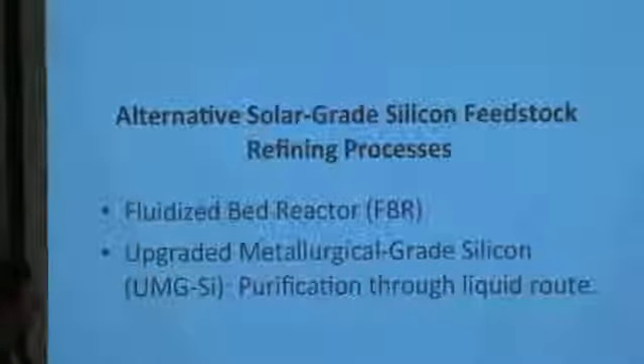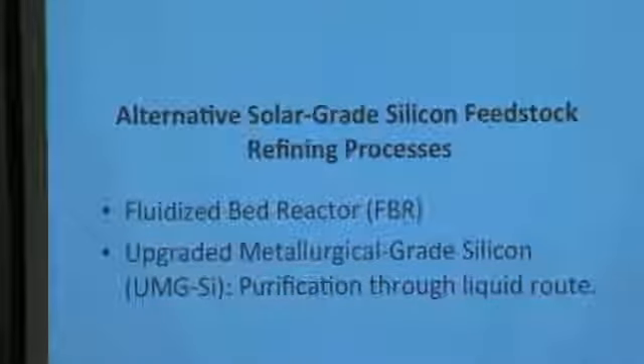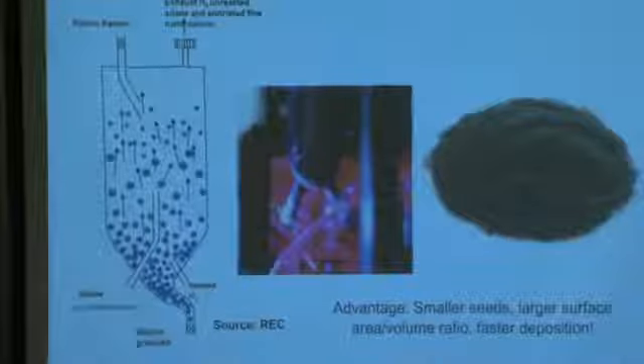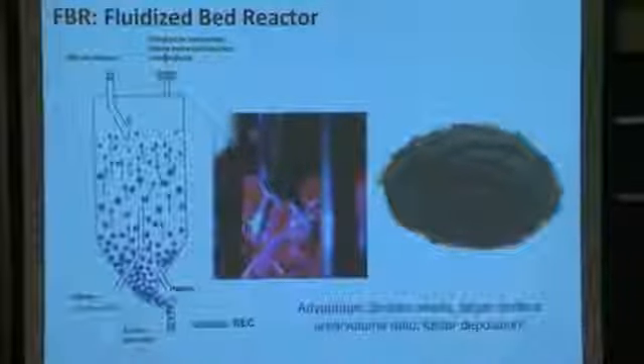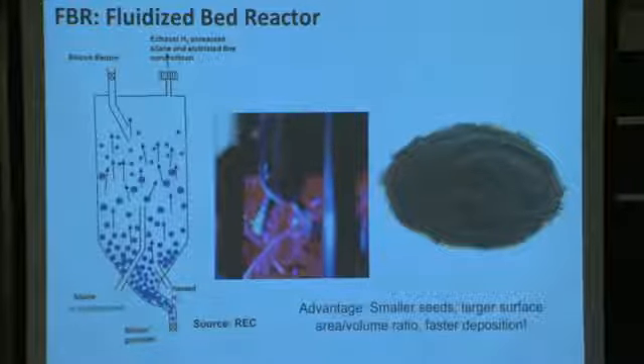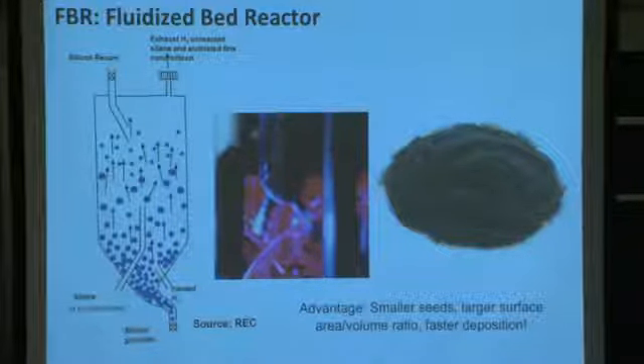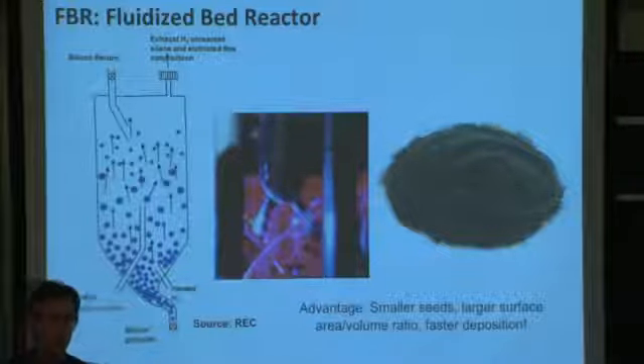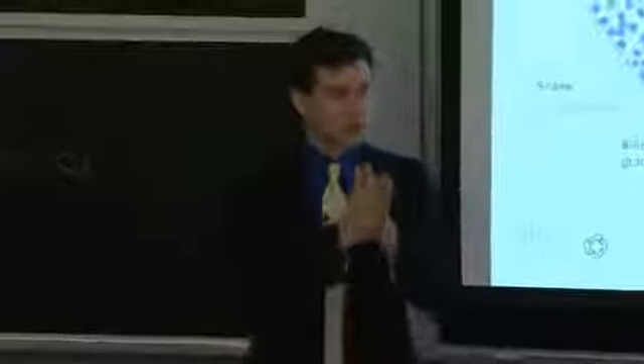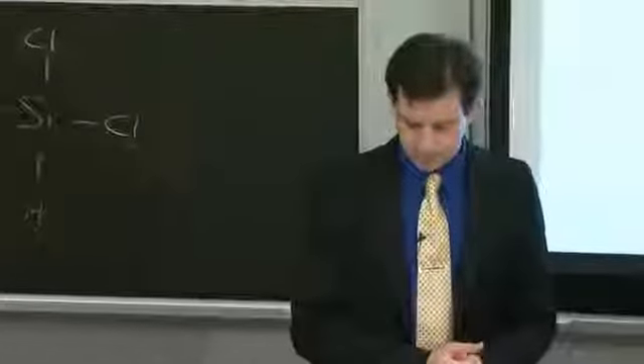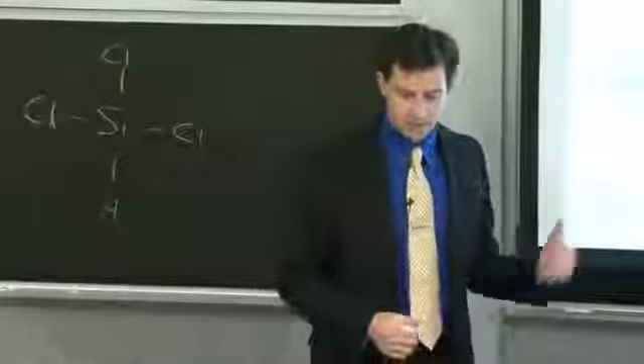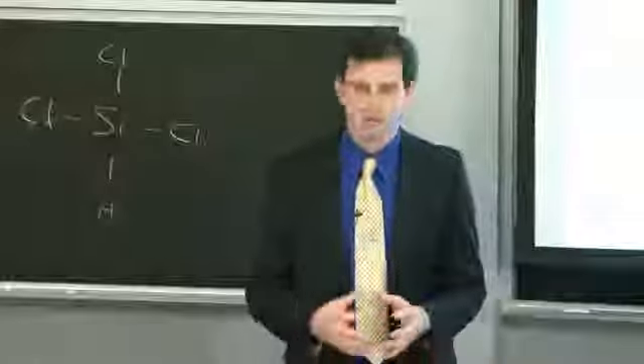So fluidized bed reactor and upgraded metallurgical grade silicon. Let's talk about each of those in turn. What the fluidized bed reactor folks realized was, gee, if we're depositing on a rod, our surface area to volume ratio is going to be very small. Think of it this way: a sphere would be the quintessential example where you'd have a very large surface area to volume ratio. If we had a plate, we would have a very large surface area to volume ratio as well. And in the case of the condition prior, where you have this rod, you really can't deposit that quickly.